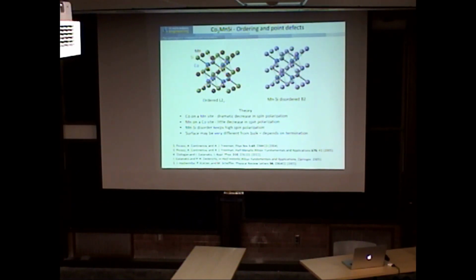Now let's go back a little bit and worry about defects. Theorists ask, how good ordering do we need for these different crystal structures? What I'm going to point out here is that if cobalt goes on a manganese site, that would decrease the spin polarization dramatically. Manganese on a cobalt site, not so much of a problem. Manganese silicon disorder, if I disorder these, I end up with B2 crystal structures, basically cesium chloride. That shouldn't have too much effect on the spin polarization.